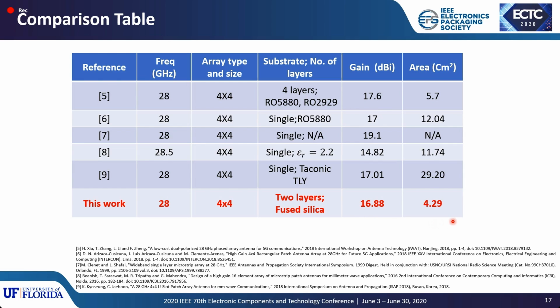And it is important to know that this demonstrated work has the smallest footprint compared to the other existing architectures. It is also to be noted that the single substrate designs have relatively more footprint compared to the multi-layers. This is because on the single substrate you have the feeding lines and the patches, everything lying on the same layer. In order to reduce the coupling effects, the patches are usually spread, or the distance between the patches is slightly increased compared to the multi-layers.